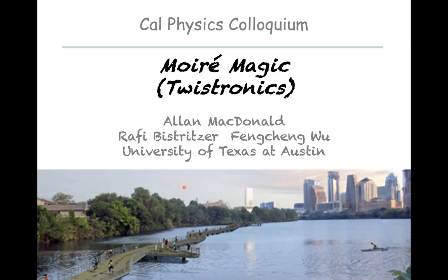It seems like a scanning probe with the right kind of spatial resolution could do it. There is this Moire periodicity on a 10 nanometer scale, and the magnetic length, or distance between vortex cores, at 1 Tesla is not so much bigger than that. So the vortices should be very strongly pinned. In terms of the effective lattice constant of these systems, at Hc2 the coherence length is very close to a Moire lattice constant, just a couple of Moire lattice constants. That's certainly something I'm extremely interested in, and I'd be very interested in chatting with anybody who thinks they know how to attempt such an experiment.